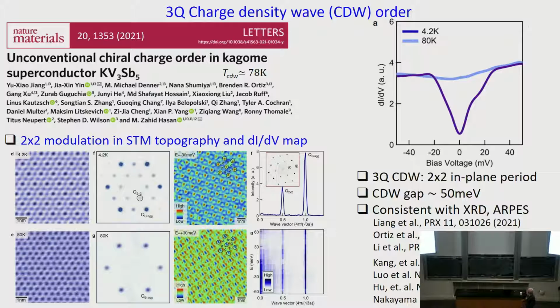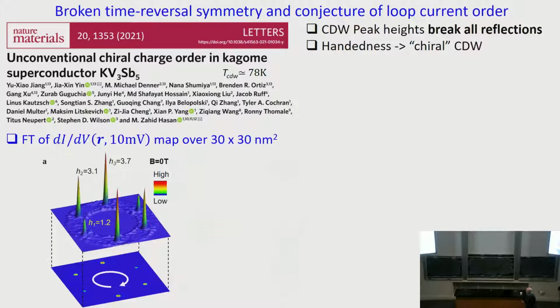All right, so this is not surprising. What's surprising is we took a closer look at these CDW peaks, the 6 peaks in the Fourier transform that is at half of the Bragg wave vector. That says there is additional translation symmetry breaking, charge density wave order. Turns out they have all different heights. Now, 2 of them, across the center, should have the same height. That was given by just the nature of STM spectroscopy and Fourier transform.